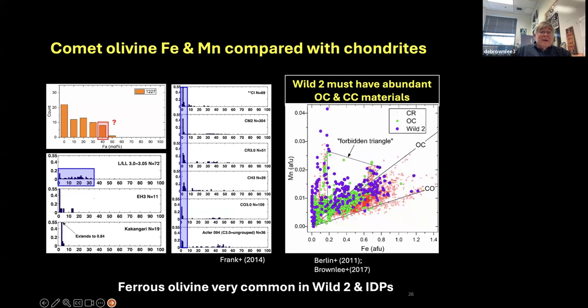So we can compare them in various ways. One is just looking at the histogram of the iron content. A big difference between the comet and most meteorites is that we see such a huge range in iron contents of the olivine, going from zilch to about FO50 or even more, which requires more and more oxidizing conditions to put that much iron into the olivine.